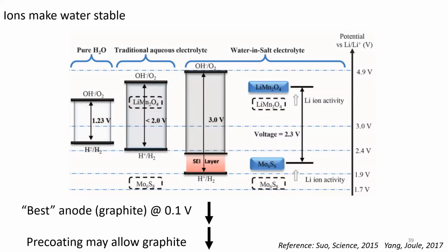They found in their prototype battery that they formed an SEI layer, that protective layer on the anode that lets the lithium ions through, but not anything else. It protects it from being reduced. That hadn't been done before with a water-based electrolyte solution. That only formed at their super high concentration. The lower concentration solutions, even though it's the same atoms and molecules involved, didn't form an SEI. So that helped boost the window towards 3 volts.